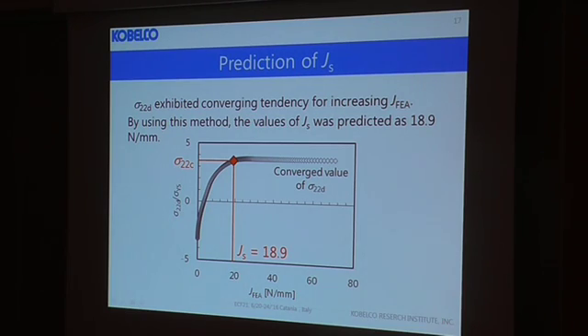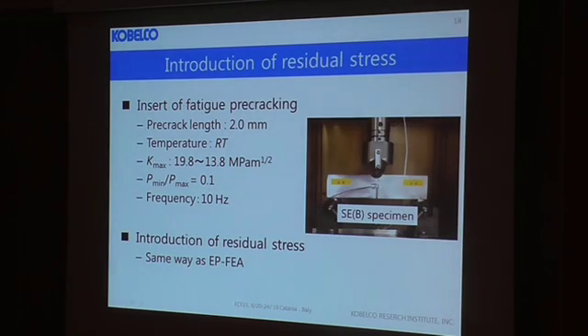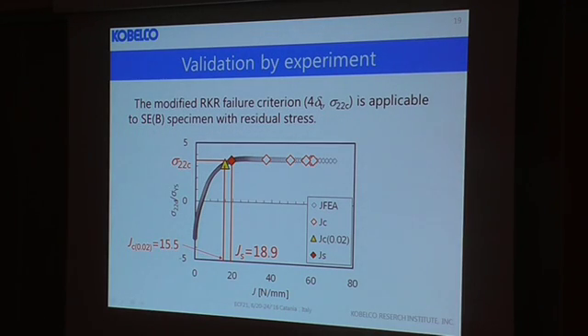And next, we performed the fracture toughness test to examine the validity of this method. First, a fatigue pre-crack of length 2 mm was inserted into the specimen at room temperature. Then after the residual stress was introduced to the crack tip in the same way as EPFEA, the temperature was changed to -10 centigrade. The fracture toughness test was conducted in accordance with ASTM E1921.